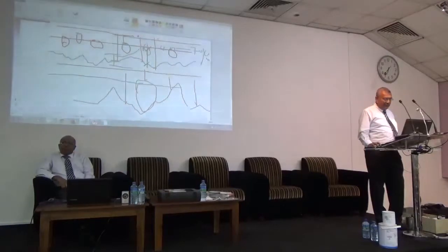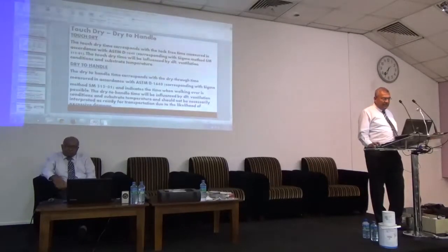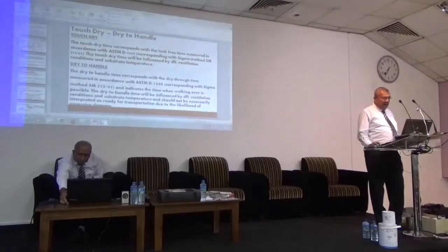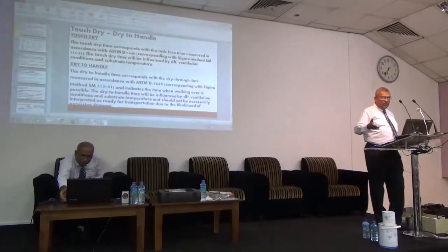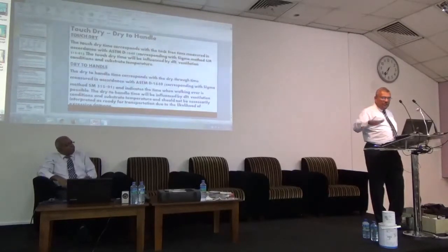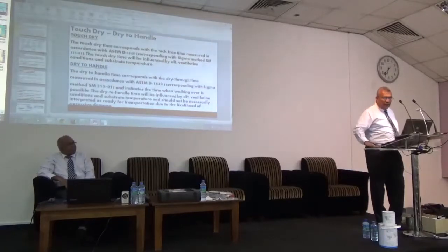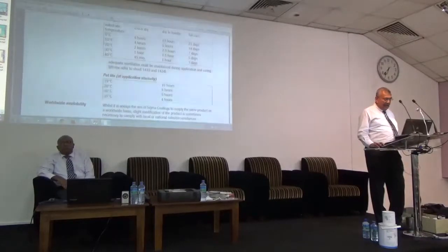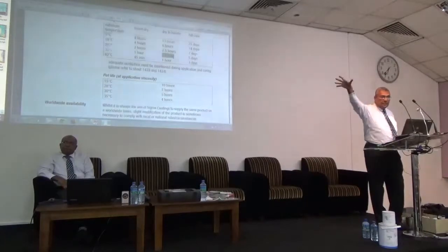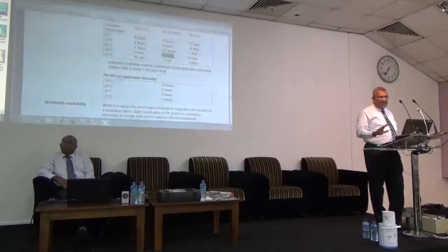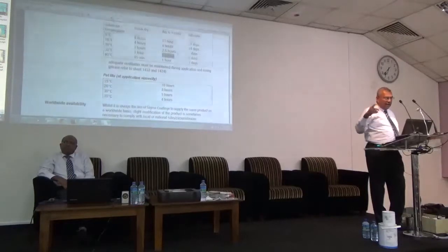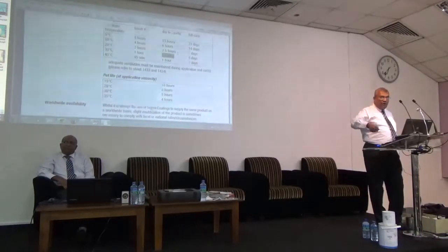The thickness will not come. So that's the meaning of touch dry. Touch dry is you apply today and 1 hour after, the dust won't get into the paint. That's okay. But until 2 hours or 1.5 hours lapse, don't carry it and put it somewhere else. Touch dry doesn't mean dry to handle. You have to have another 1 hour, 1.5 hours for you to carry it.